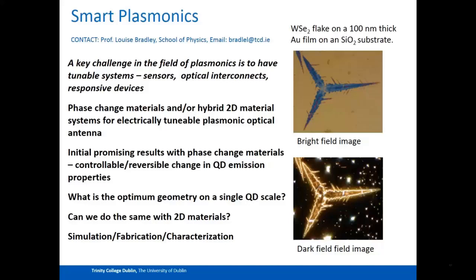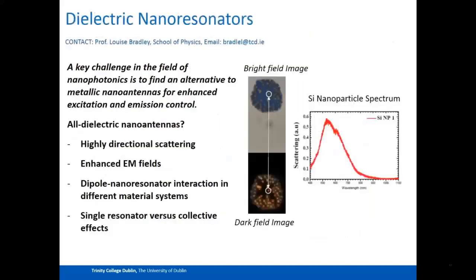So we use these 2D materials, and we use vanadium dioxide, which is a phase change material. It changes from semiconductor to metallic under different conditions, to make these plasmonic structures, these nano antennae, dynamically tunable. That's one kind of thing we work on. Now, one of the problems with metals is that they're lossy. At the moment, they're the best option that there is, but the losses are a big drawback. So what can you do if you want to do nanoscale photonics with a less lossy material? We start to think about nanophotonics using dielectrics.